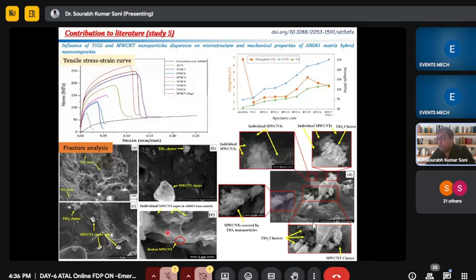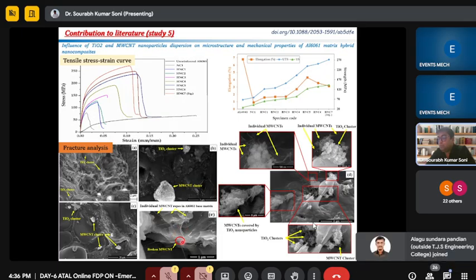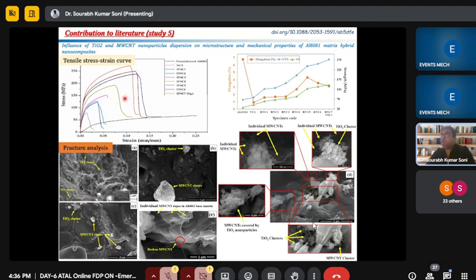Okay, study five. So from this FESEM image, we can observe the MWCNT ropes also. That's why I said that FESEM is more popular and more useful than the SEM image. So if you are going for nanoparticles, go for FESEM. Here are the TiO2 clusters and MWCNT clusters, which are responsible for the ductility decrement. So we can relate this. Here also, in another route, I have observed this kind of pores filled with MWCNT TiO2 clusters. So I can say that this processing route is not good. Here there is an agglomeration kind of observation.